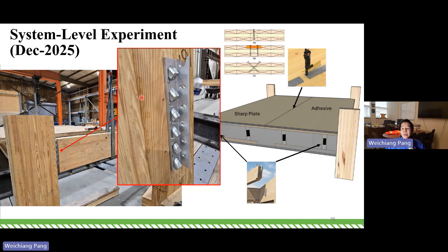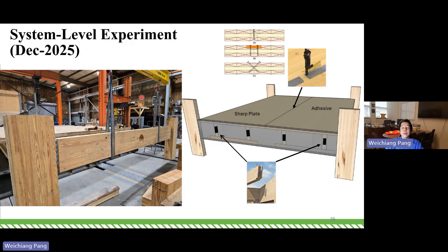Yeah, this is a very good point. You pointed out the issue here, because due to the limitation, we do not want to build the full system and then just take it apart, because it takes quite a bit of effort and resources to build the full system. Yes, if the system is put together and only subject to service level loading, without seeing the overload destructive loading, taking apart the CLT panel and glulam would likely be challenging, because the adhesive is in full bonding. That is why we also have a second design using the Rothoblaas system. The Rothoblaas system, we tested at the connection level. We can easily take it apart after we put it together. We can separate them. Yep, you're right.